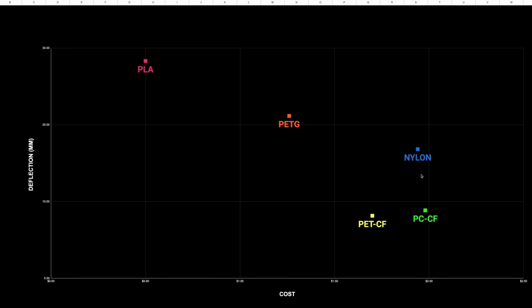The nylon didn't perform very well, and unfortunately I found out during the test, deep within the data sheet, that it prefers to be annealed post-printing. So I did end up annealing this part and it still didn't perform very well and it shrunk. So if I had to do this over again, I would not even test this part because it's disqualified for being too fussy, and I would have tested something else.